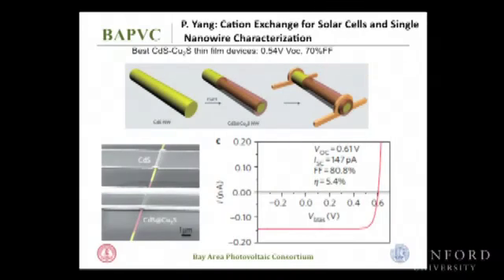Now the open circuit voltage can reach 0.61 volt. It's very high. And the fill factor is 80%, compared to these parameters. Now you start to see a surprising result. Even a single nanowire's power conversion efficiency gets up to 5%. Now this is a technique to really come back to look at the materials system you're developing, down to the single nanoscale grain, to understand what's happening.